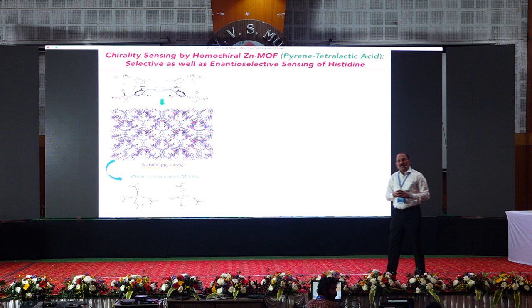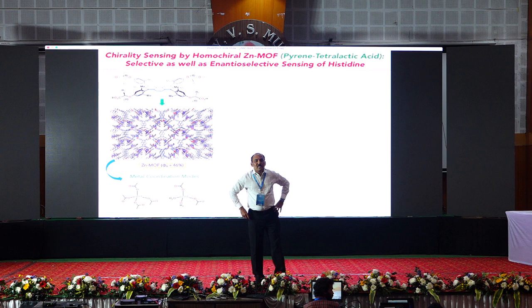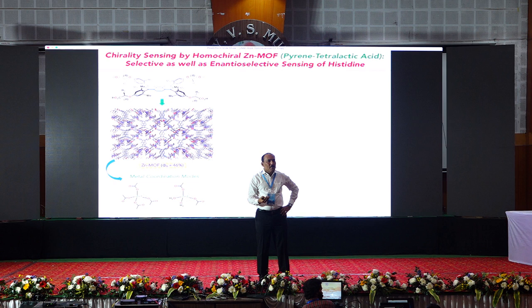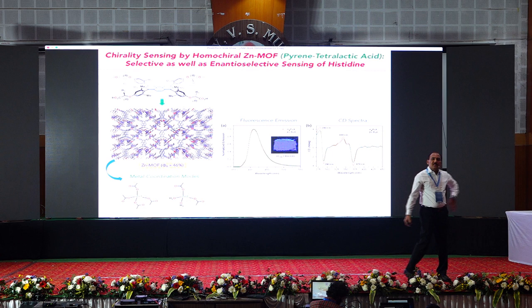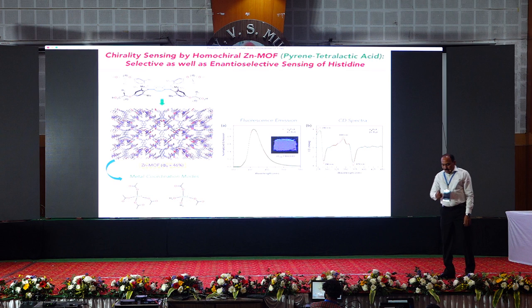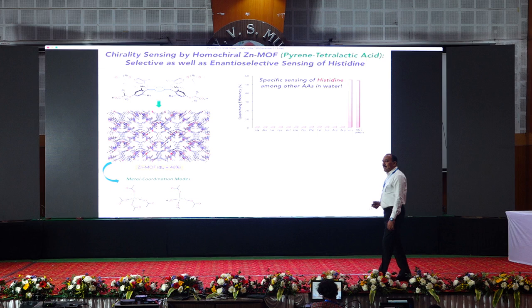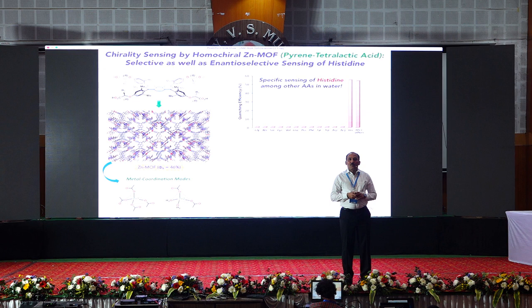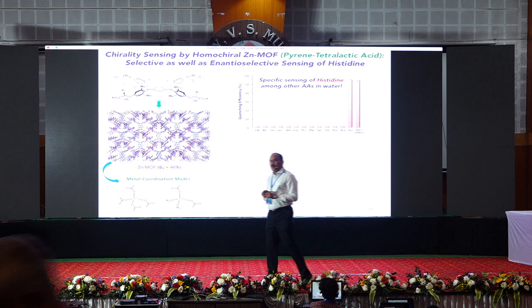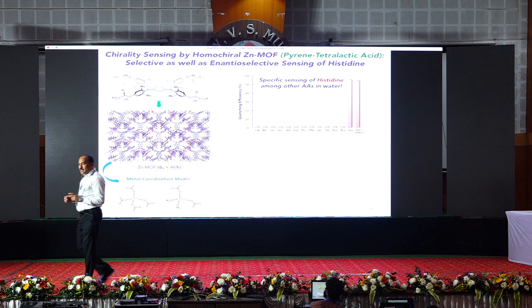If that is the case, and given that the pyrene is a flat molecule that is fluorescent, can we use this for signaling whatever goes into the pores, as a sensory material? I'll not delve into the details, just to show you it's brilliantly fluorescent because self-quenching is hindered by having paneling. And you can worry about the CD spectra. There is some intuition with which we build and demonstrate that we have 20-plus natural amino acids, all are chiral. And it turns out that of the 20 amino acids, only one amino acid is selectively sensed by this material. So take this dispersion of this material and put in all amino acids, the fluorescence is not disturbed, except with one amino acid, that is histidine.